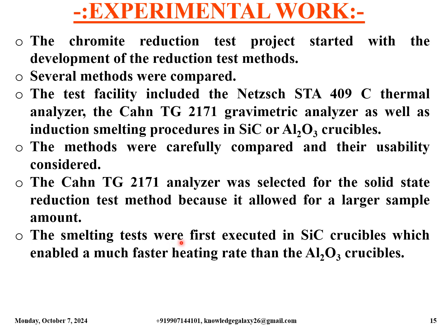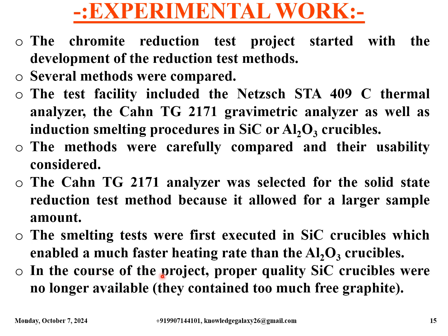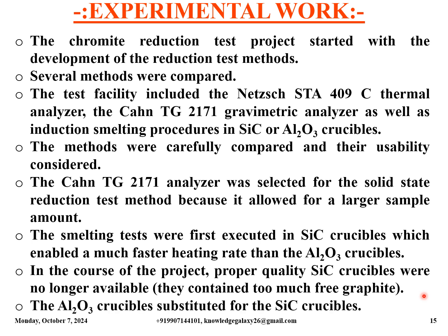The smelting tests were first executed in SiC crucibles, that is silicon carbide crucibles, which enabled a much faster heating rate than the alumina crucibles. In the course of the project, proper quality silicon carbide crucibles were no longer available. They contained too much free graphite. The alumina crucibles substituted for the silicon carbide crucibles.